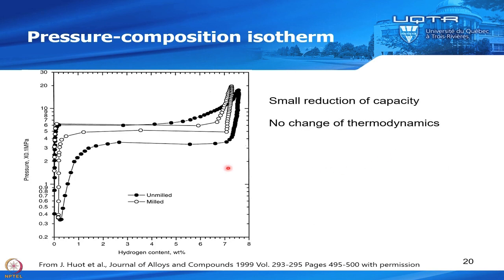But this is the thermodynamics. So this is the pressure composition isotherm, as we saw in one of the first slides. So this is the unmilled one. So the unmilled one, you have your plateau, as we saw in the first slide. And then you have the absorption, and after that you have the desorption and you have a plateau again.